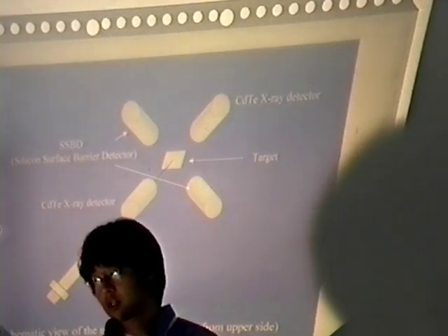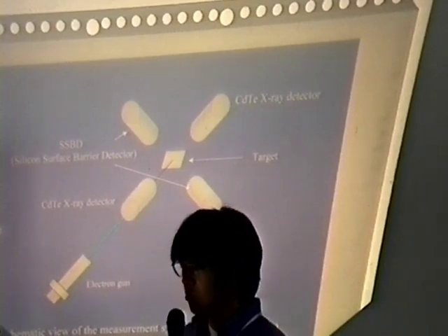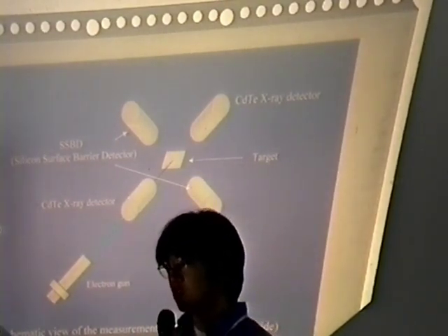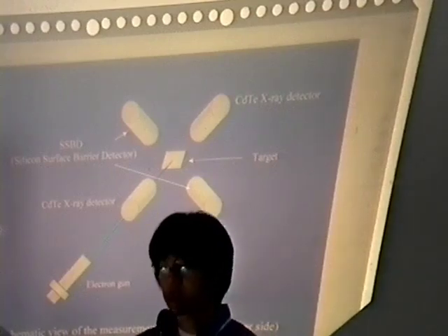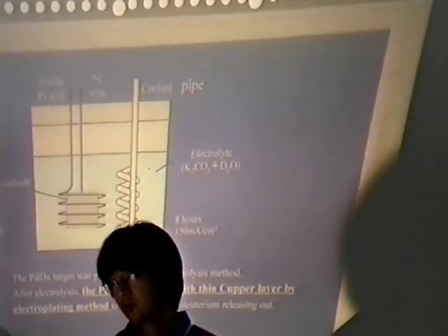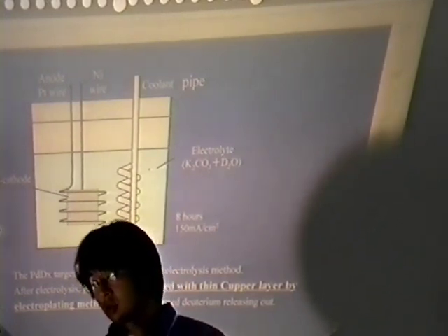And we used PdDx or TiDx as a target in this experiment. TiDx was prepared by using a gas loading method, and PdDx was prepared by using the electrolysis loading method. And after the electrolysis, the palladium deuteride was coated with a thin copper layer by electroplating to prevent the trapped deuterium from being released.